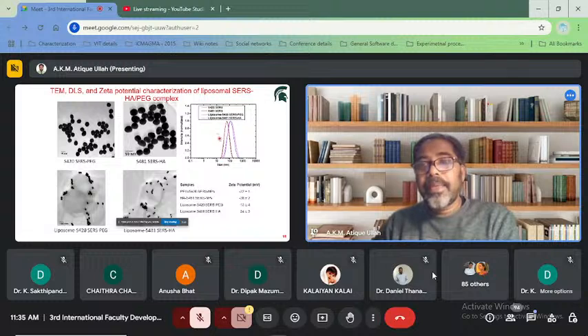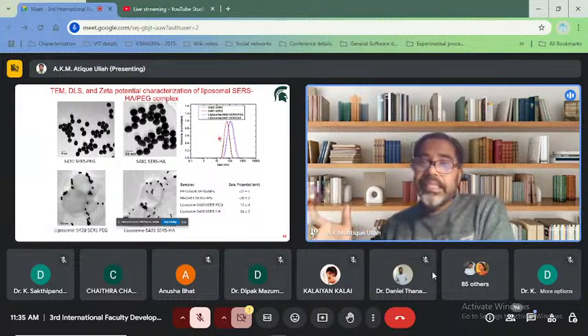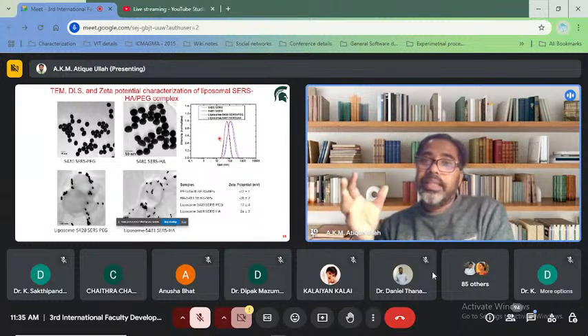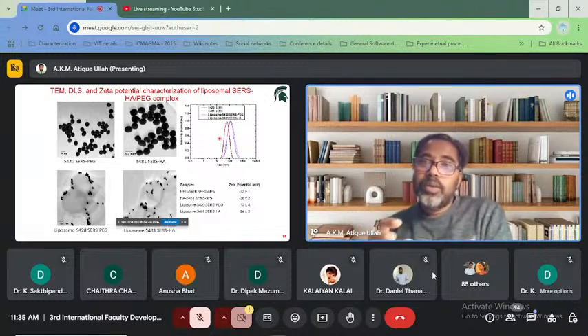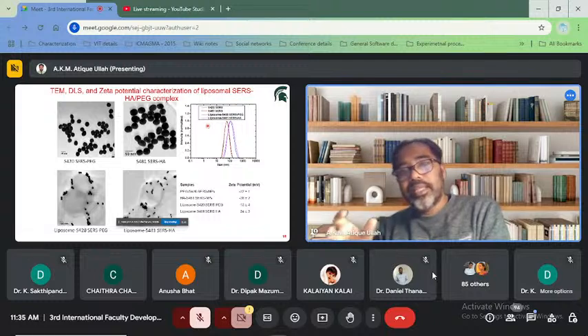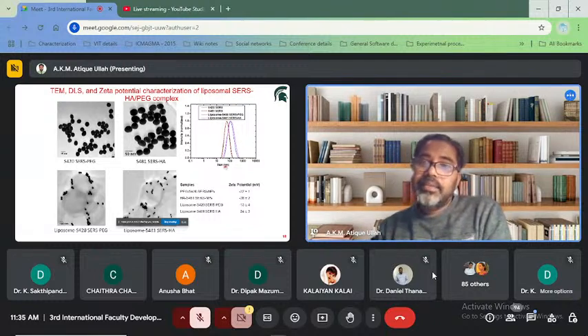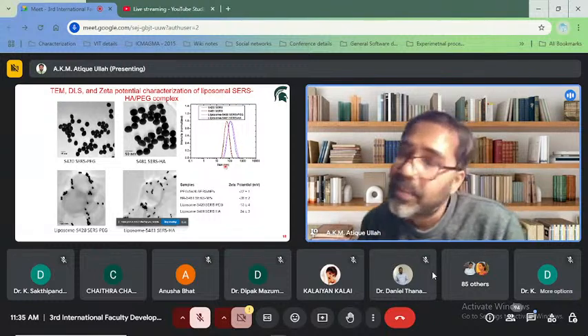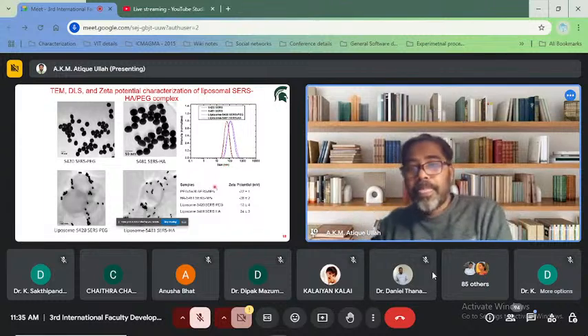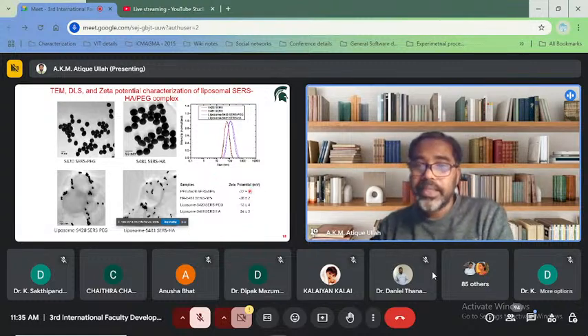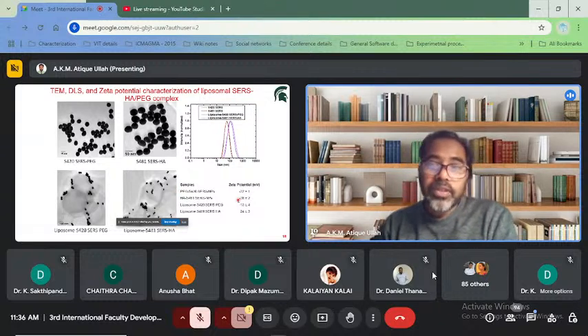You can see the hydrodynamic size is increased when the particle is a liposomal complex. So when there is an increase in the diameter, this is an indication that the liposomal complex is formed. And also you can see there is a change in the zeta potential before and after the formation of the liposome complex. This is also an indication of the liposomal complex formation.